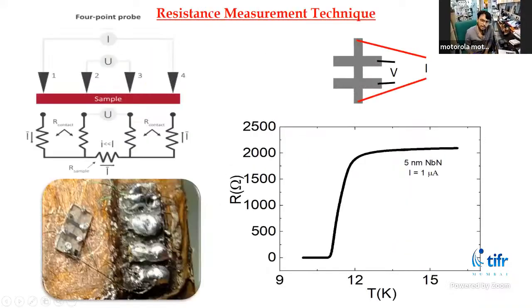So for being a superconductor, as Rishabh has described, it has two basic properties: zero resistance and the Meissner effect. For measuring the resistance, we do a 4-probe kind of measurement. We pass current from these two leads, and we measure voltage from these two leads, and we check the resistance. So when a particular film is superconducting, below a certain temperature its resistance should go down to 0 ohm. I'm showing you the plot of temperature versus resistance.